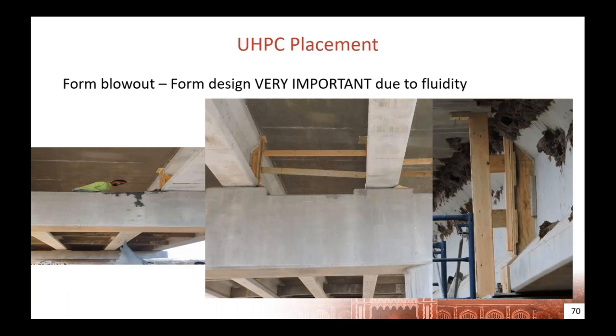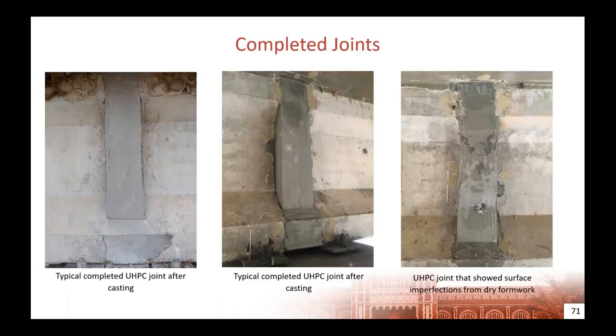And for the exterior joint, they braced it against the bridge deck and the bent so they wouldn't have any form failures after that. Unfortunately, there was one minor incident when they started pouring one of the last joints, but they were able to correct it while placing other joints. So there was no major issue after this first form blowout, and everything went smoothly. So after the joints were completed, this is what they look like after the formwork was removed.